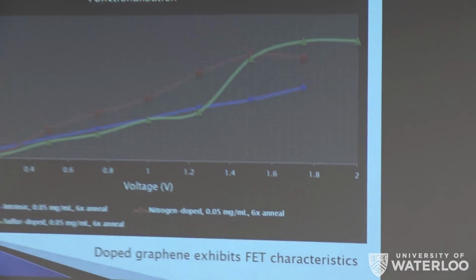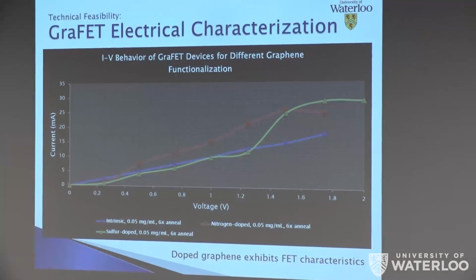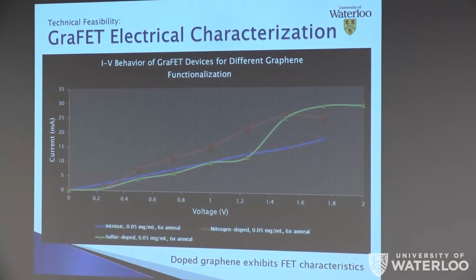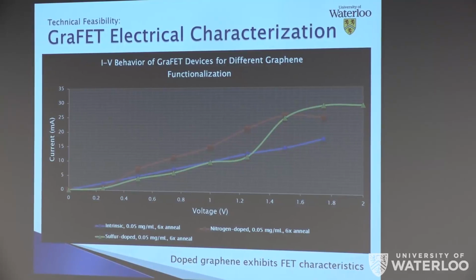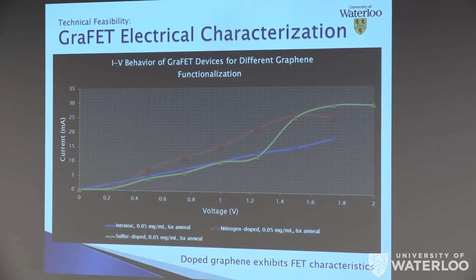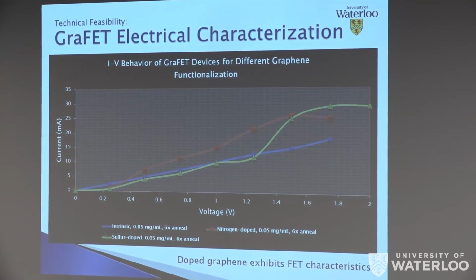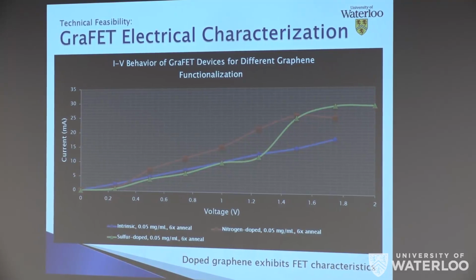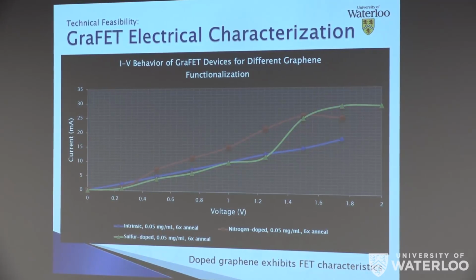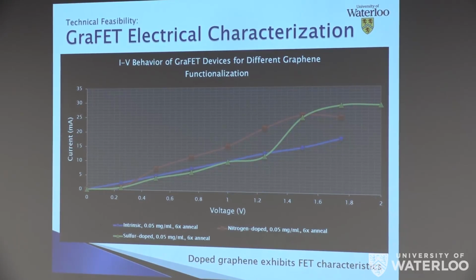Red is nitrogen-doped graphene, and green is sulfur-doped graphene. So for this experiment, we ranged the voltage and measured the current. And you can see for the two doped cases, at high voltage, the current plateaus, which is characteristic of field effect transistor devices. And while this data is less than perfect, it is preliminary data. And based on this, we were confident that our device would perform as expected in a gas environment.